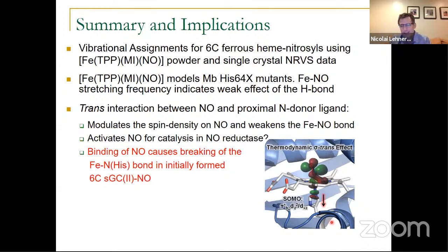So this whole helix here swings back when the histidine falls off the iron center here. So the binding of NO through this sigma trans effect causes the breaking of the iron-imidazole bond, and then that activates soluble guanylate cyclase.